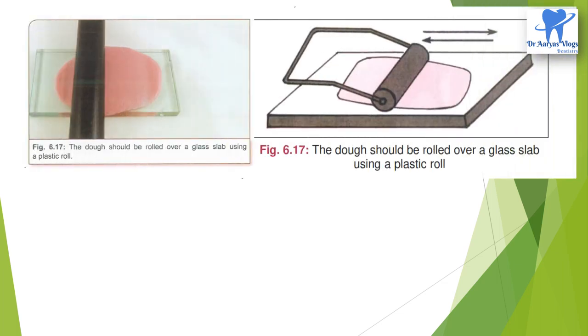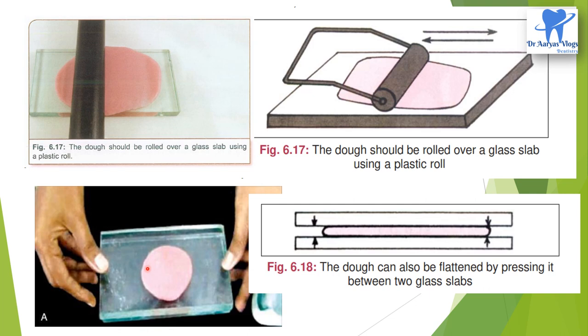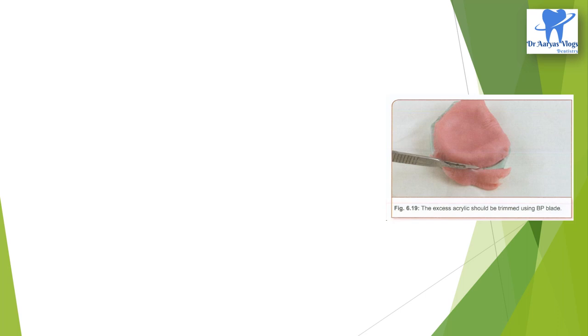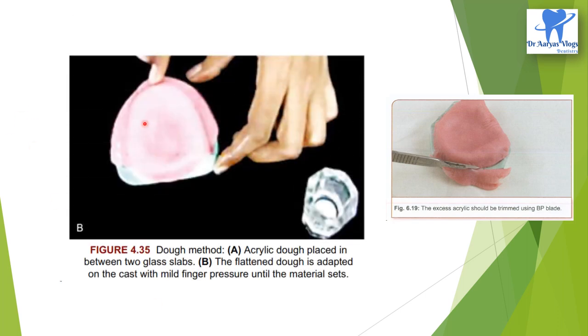Coming to the procedure, manipulation is done in the late stringy or dough stages. The material is kneaded in the hand to achieve a homogeneous mix, and then shaped into a 2 mm thick sheet. The flattening of the dough can be done by rolling it over a glass slab using a plastic roller, or by pressing it between 2 glass slabs. Separating media should be applied over the roller or glass slabs to avoid stickiness. So this is the flattened dough, which is adapted on the cast with mild finger pressure until the material sets.